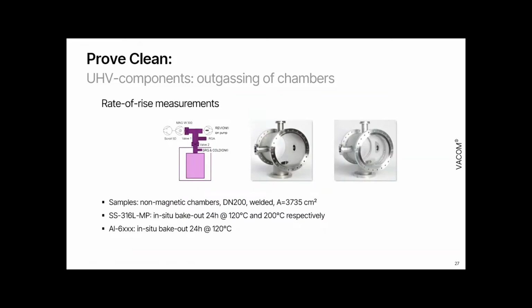So here I will show you the difference in rate of rise measurements and outgassing of two chambers. One is a stainless steel chamber that was baked at 120 degrees for 24 hours and 200 degrees for 24 hours, compared to a full aluminum chamber that's been baked out for 24 hours at 120 degrees. And then we take a look at the outgassing rates.